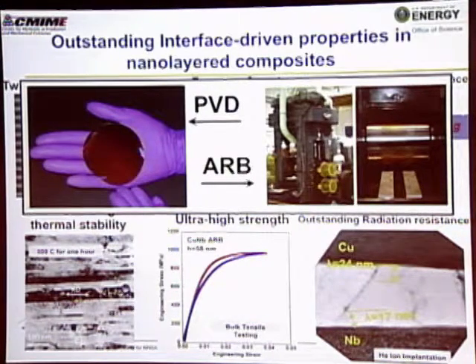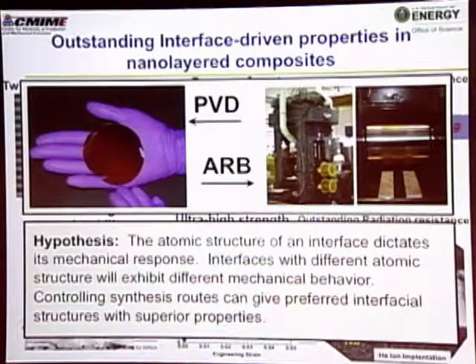until the material bonds. So the issue here is that if we use different synthesis techniques, we'll get different types of interfaces. So we can form a hypothesis, and that's that the atomic structure of an interface dictates its mechanical response. Interfaces with different atomic structure will give you different mechanical behavior, and if we can change the synthesis route, we can get preferred interfaces with superior properties.